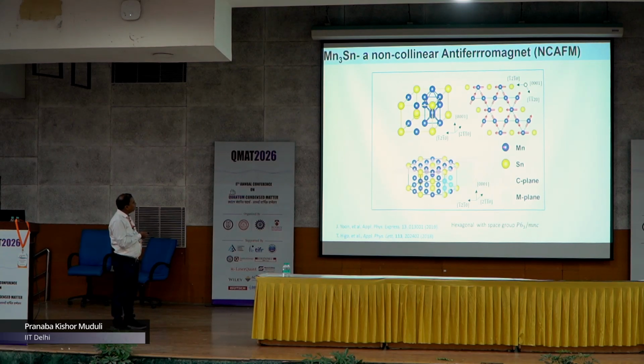Here, if you look at the blue ones, they are actually manganese, and the yellow is tin, and you can see that they are non-collinear. The overall magnetic moment will be zero because of the arrangement, but it is a very complex arrangement of magnetic spins, and this sometimes leads to a little bit of tilting of the magnetic moment out of the plane of the Kagome, and often this structure is defined by something called the octupole moment that I will be talking about later on.